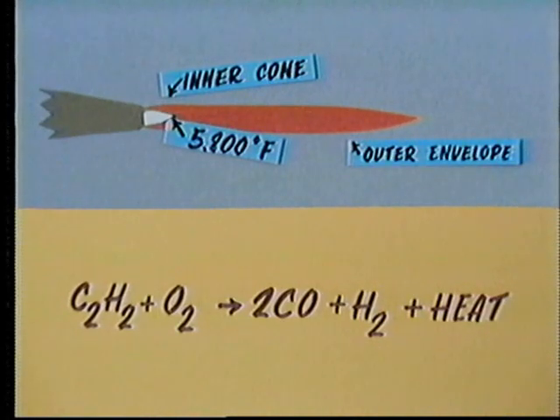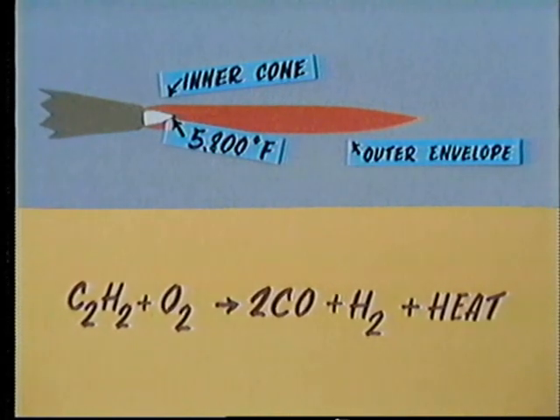The equation illustrates what is happening at the outer edge of the inner cone. Acetylene plus oxygen yields carbon monoxide plus hydrogen plus heat. One molecule of acetylene combines with one molecule of oxygen, yielding 2 molecules of carbon monoxide and 2 atoms of hydrogen. Since the oxygen in the primary combustion is not supplied from the air, the flame has a relatively high temperature at the tip of the inner cone, approximately 5,800 degrees Fahrenheit, and is highly concentrated.